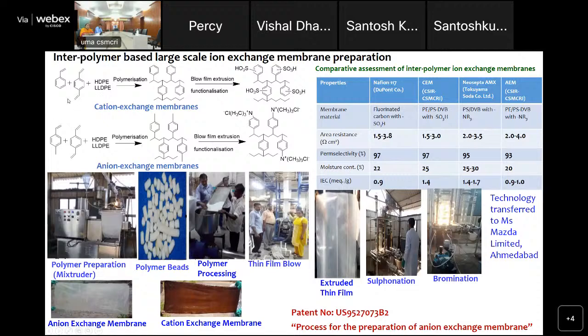We have polyethylene interpolymer based ion exchange membranes, which we have prepared by a melt extrusion process. This is a scalable membrane. The cation exchange membrane is prepared from the interpolymer of polyethylene and styrene divinylbenzene. Once the polymer is prepared, it is converted into a thin film of thickness 150 to 160 micron. Then, once the film is prepared, the negative charge on the membrane surface is introduced by sulfonation reaction in chlorosulfonic acid and dichloroethane mixture.